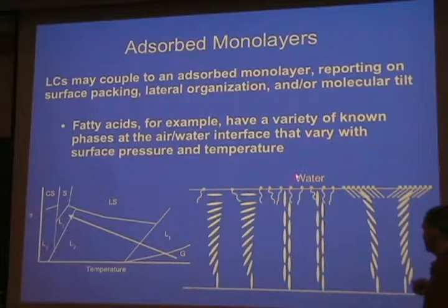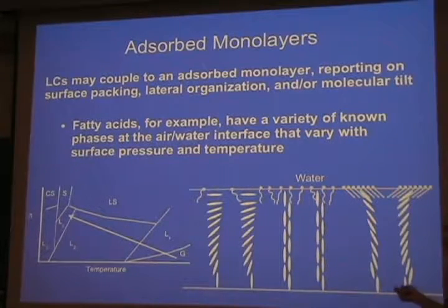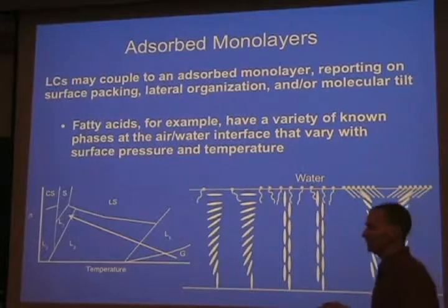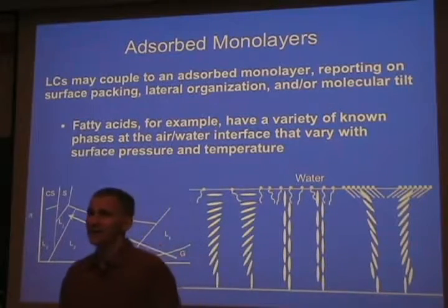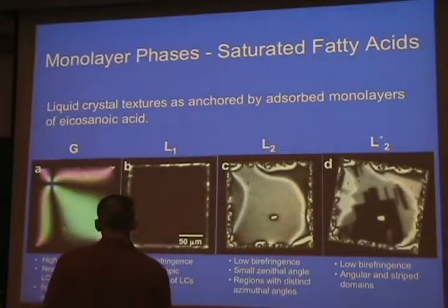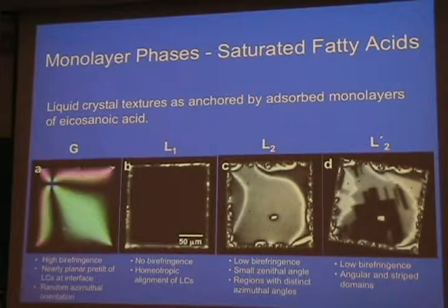If the molecules were more concentrated at the interface, but in a disordered way, then one observed homeotropic anchoring at that interface. But in some very densely packed phases where there was liquid crystalline order in 2 dimensions within the monolayer, if those molecules had a coherent tilt angle, then that tilt angle was also transmitted to the liquid crystal, and so we had an intermediate type of anchoring, and we saw birefringence. So here are some actual pictures showing birefringence.